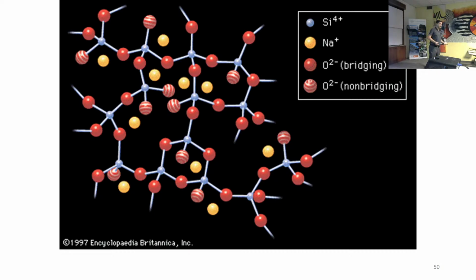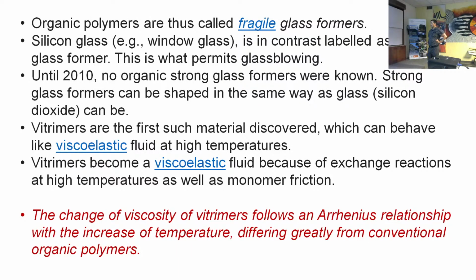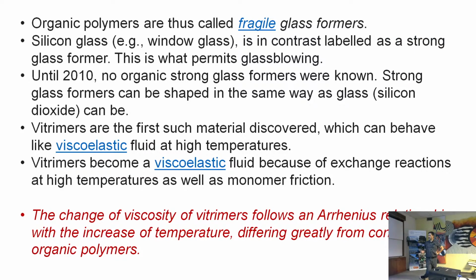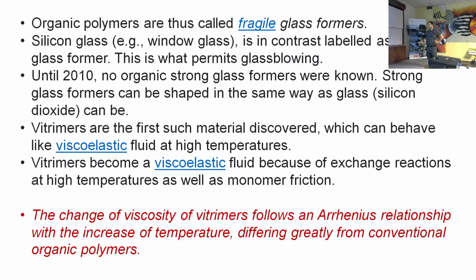In principle, there will be advantages if we use organic material. Why? Because these temperatures will decrease dramatically. And so, up to 2010, no organic strong glass former was known. Vitrimers are the first material discovered that can behave as a viscoelastic fluid. And this is quite recent, about 10 years old, the technology of vitrimers. The change of the viscosity of the vitrimers follows an Arrhenius relationship with increase of temperature. So it's very different from conventional organic polymers, and you can shape it in the ways you wish. So vitrimers have this advantage.